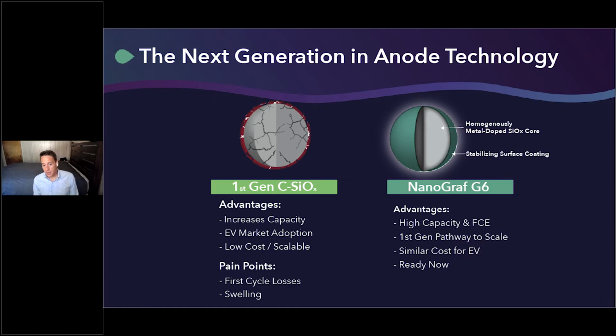So what is our technology? Again, comparing it to the first generation carbon-coated silicon oxide, which had great capacity and has already achieved EV market adoption because of, again, cost and scale. What we've been able to do is use a metal doping process to eliminate the previous pain points with carbon-coated silicon oxide. And those would be, again, really low first cycle efficiencies, which were anywhere between 72, 74, 75%, and also the real swelling problem with silicon oxide as well, which as some of you may know, as it charges and discharges, it swells, it cracks, leads to electrical disconnection, and really leads to poor cycling.